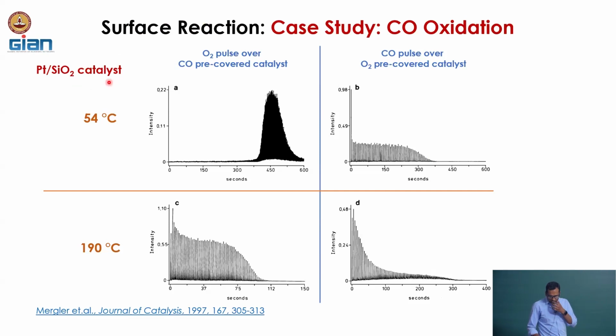And just look at the 4 quadrants. I have graphs at different conditions, okay. The top 2 quadrants versus the bottom 2 quadrants, it is pretty simple, they are at 2 different temperatures. The top 2 are conducted at 54 degrees Celsius, and the bottom 2 are at 190 degrees Celsius. Okay. Then the left 2 and the right 2, there is a difference. In the left 2, first we have given a series of CO pulses such that my catalyst surface is now saturated with CO.